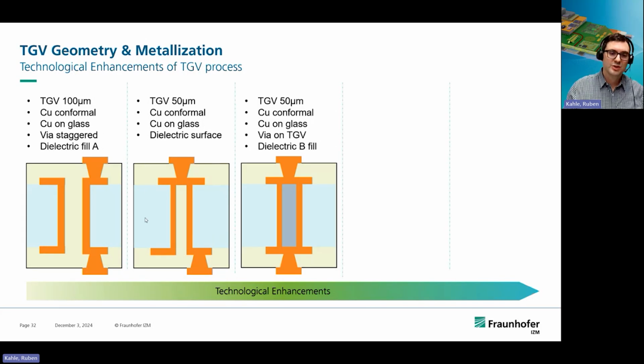More of these technological enhancements came when it was able to fill it with a dielectric, to close the TGV from both sides, so they are more compatible to the RDL processes, typically being done with spin-coated resists. But also going into large panels, we see films, for example. But it's always good to have a closed one, to have not an air gap in between. But this is only from the processing side. It is always important to also look at the TCT tests and the reliability of this. But this could be better.